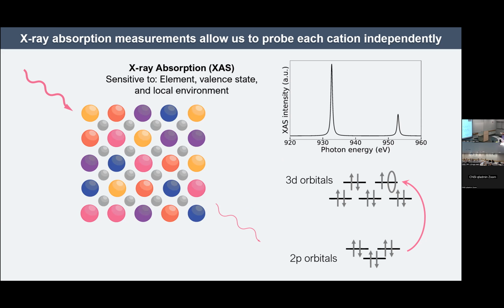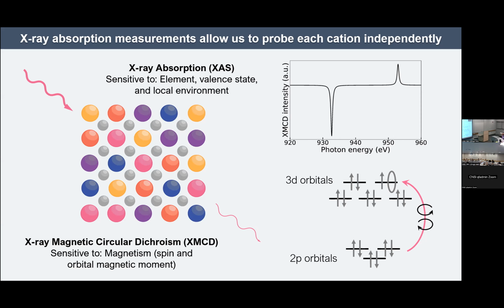The energy at which these absorption processes occur is exactly specific to a given element. Based on the valence state, which dictates the number of holes in the 3d band, we learn about the valence state of the element. And based on the way that those levels are split, we learn about the local environment, whether it's tetrahedral or octahedral. These are basically all of the questions that we would like to answer about these high entropy spinels. And there's an added bonus: if we perform the exact same measurement with circularly polarized light, a technique known as X-ray magnetic circular dichroism, we pick up a degree of sensitivity to the orbital and spin degrees of freedom.